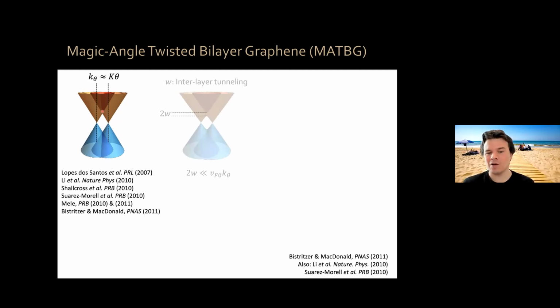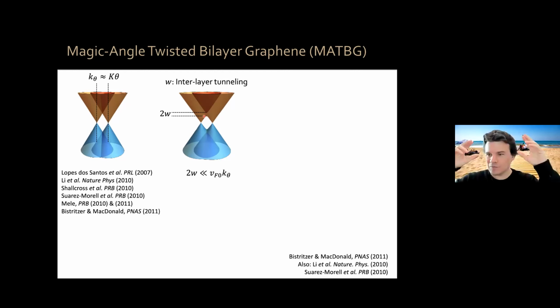So they can form bonding and anti-bonding states, which open a gap at the point where you have that intersection. This interlayer tunneling leads to the opening of a gap, and in particular, the bonding state gets pushed down in energy a little bit. Now, this is very similar to bonding and anti-bonding states in a hydrogen molecule, but what we have now is a giant graphene molecule. Now, the situation is what happens when this interlayer tunneling energy is smaller than the energy of that crossing point.